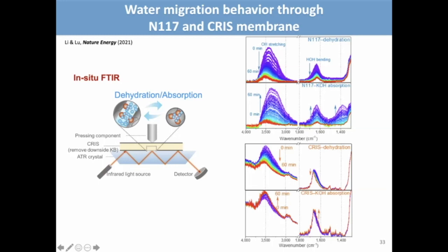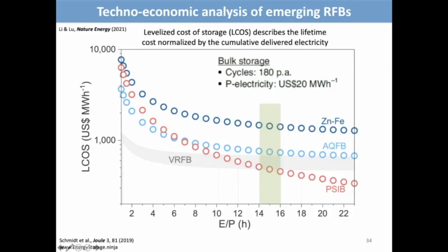We also performed in-situ FTIR to try to understand the water migration behavior through the membranes. So what we did is we performed a hydration and dehydration process and tried to measure the water content in the membrane through time. So you can see with the commercial membrane, the water can go in and out through dehydration and absorption very quickly, but that of the modified membrane has much restrained water migration and water mobility. So that is also consistent with the stable cycling.